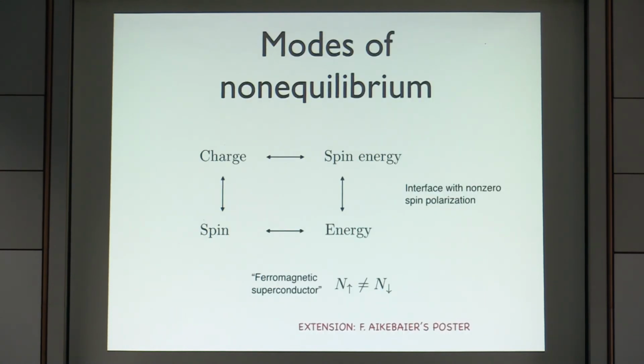What you see in this system is a structure where charge and spin energy are always coupled, and spin and energy are coupled. If you have an interface with non-zero spin polarization, then you can couple in the vertical direction, which leads to a coupling of them all.